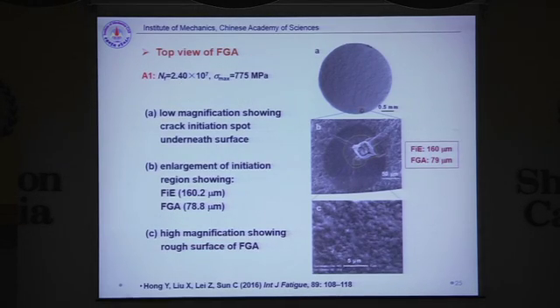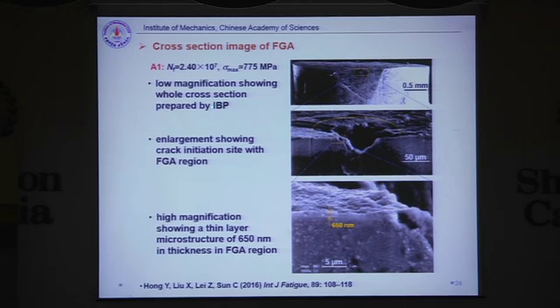And for the red one, it failed in a very high cycle fatigue regime. And this is a top view from low magnification to high magnification to show a rough surface during the crack initiation process. And then we use the method of ion beam polishing to get a kind of profile sample, and we observe this initiation region to see there's a layer about 650 nanometers of rough surface.